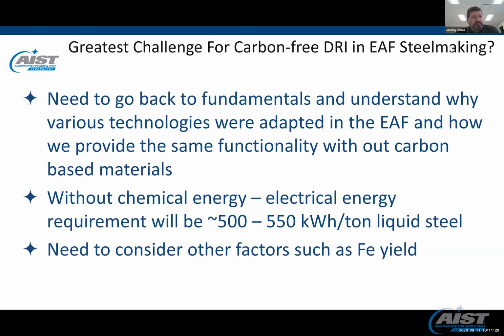So if we don't use fossil fuel to provide energy at those cold spots, do we use hydrogen-based burners? Do we use maybe ammonia-based burners? Do we use plasma torches? There are a number of different options which we'll have to look at. But what happens when you remove a lot of the chemical energy from the furnace is that we're going to require a lot more electrical energy, probably on the order of 500 to 550 kilowatt hours per ton of liquid steel. And that isn't an issue because we're assuming that by the time we do this, we'll also have renewable energy. So our electricity won't have a carbon footprint.